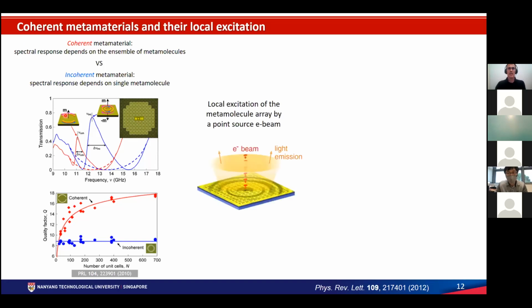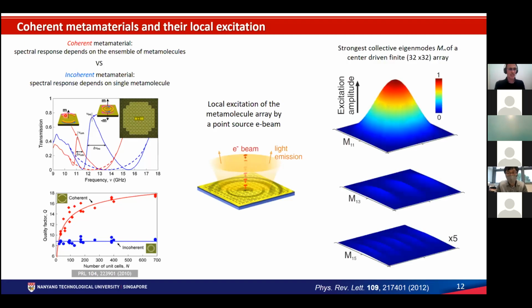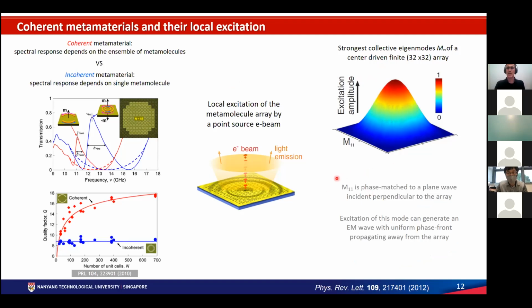So the real question is, can you actually generate such a mode? Can you engage such a mode by exciting the structure at a single position? It looks like you can. So we did the theoretical estimate. We described the metamaterial as a set of dipoles that are oscillating in antiphase, one against the other, and we drive it through the center. You can see that there are three main modes supported by the structure. But the one that has the highest strength is this M11 mode, which is actually phase matched to a plane wave that is incident perpendicular to the array. So the excitation of this mode locally from the center can generate an electromagnetic wave with a uniform phase front that propagates away from the array.